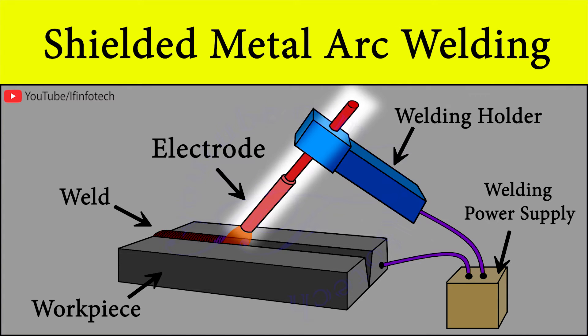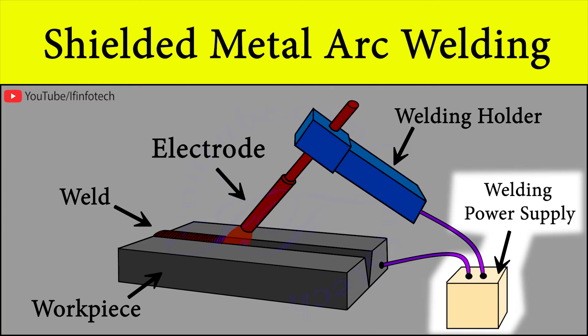The choice of electrode and welding position also determines welding speed. The flat weld requires the least operator skill and can be done with electrodes that melt quickly but solidify slowly. The power supply used in this process has a constant current output, ensuring that the current remains relatively constant even if arc distance and voltage change.